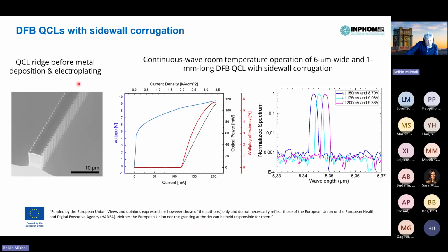For integration of the lasers, we need to integrate distributed feedback lasers, and we found that the best way to implement them in basically one single etch would be to use DFB lasers with sidewall corrugation. Since we operate at mid-infrared wavelengths, the period of the grating is longer than that of the DFB grating for near-IR lasers. Another advantage is that for inter-subband devices, you can actually etch your lasers through the active region, and all quantum cascade lasers, for example, are etched through the active region.